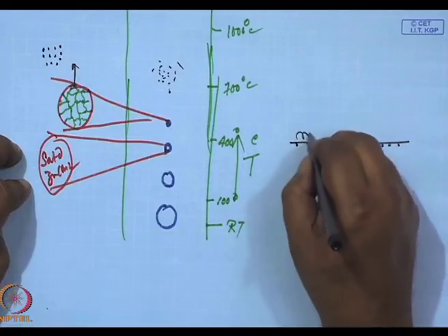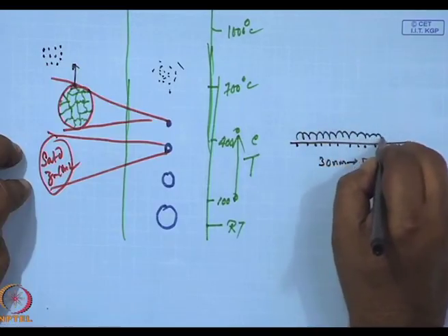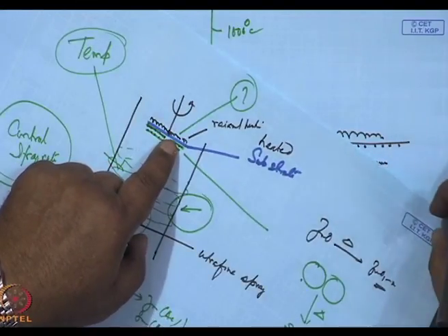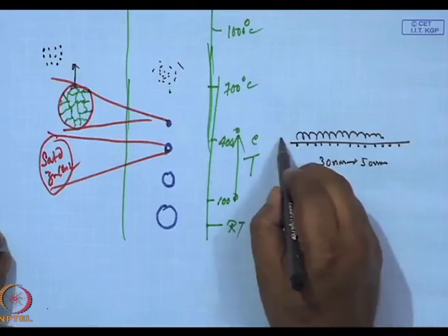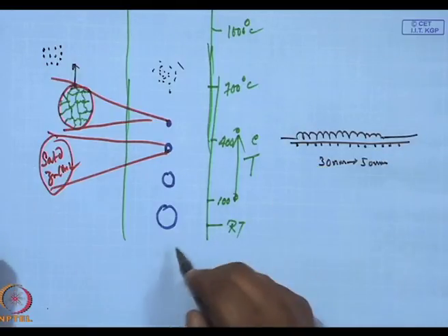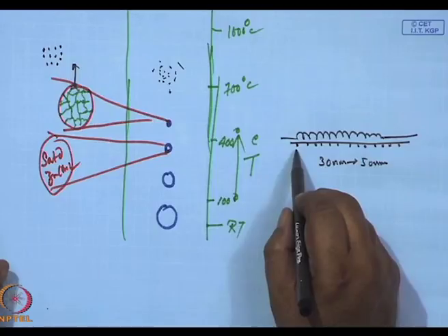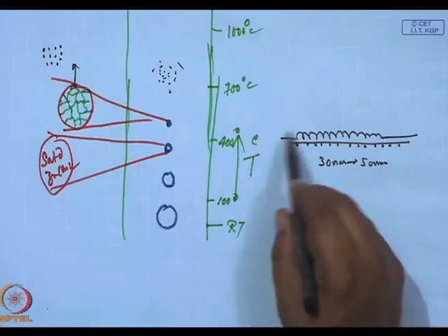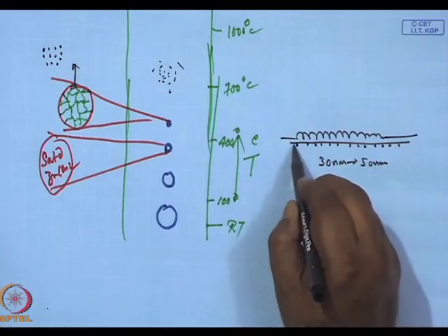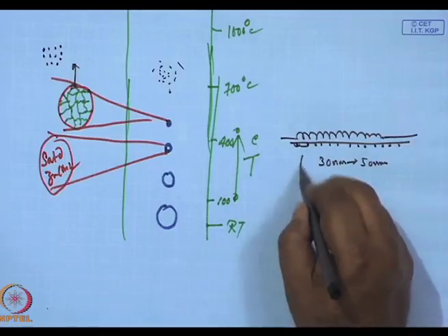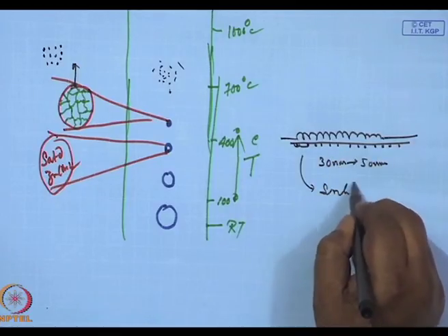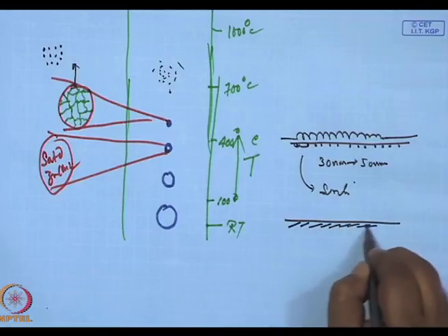Now, you have a radiant heater. Remember, I talked of using a radiant heater over here so that I could have a dense film. Now, if the radiant heater is there, then what happens? These particles, when they reach the substrate, have just gone and stuck over there. Now, with the radiant heater, they move around, spread, they sinter, and they can give you a very dense film of zinc oxide.